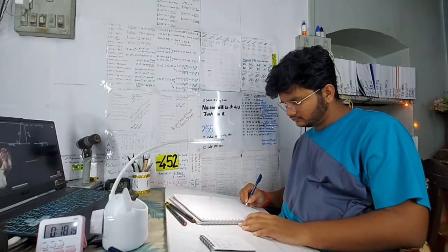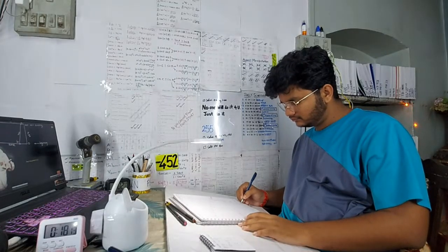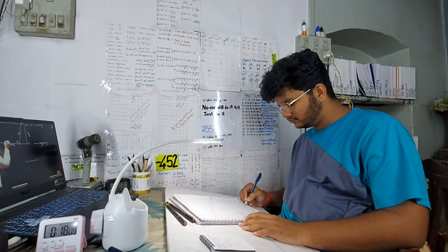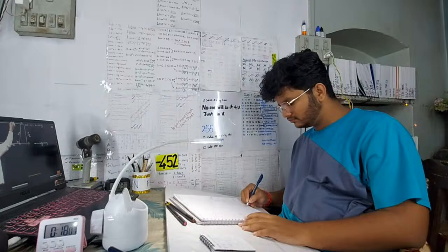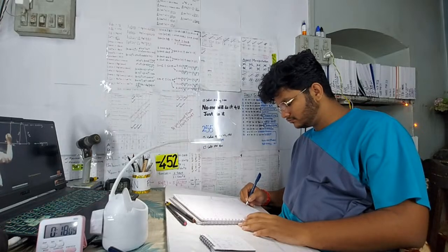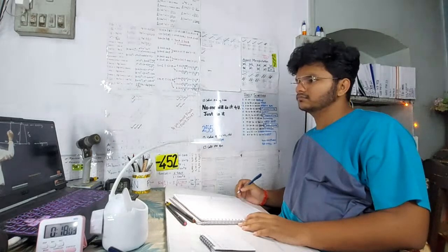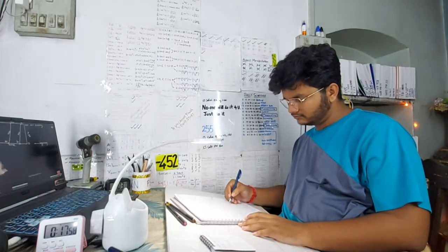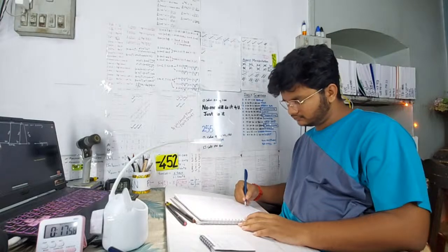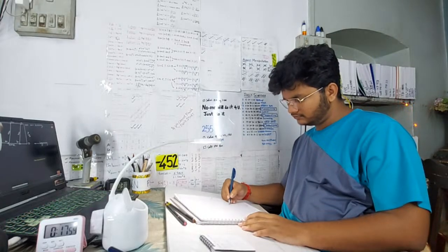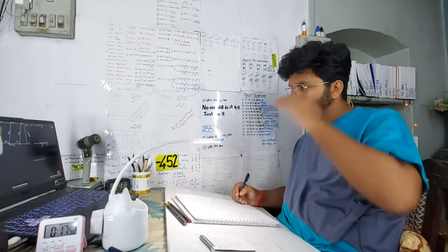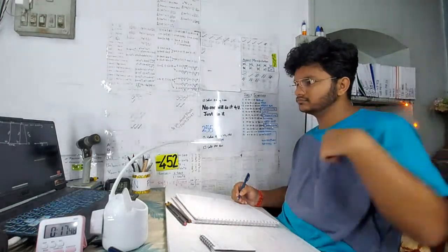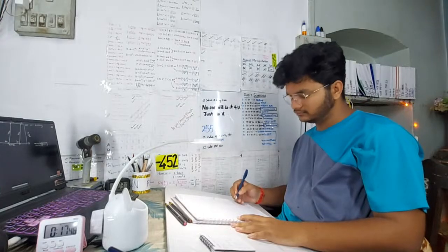Moving ahead. When you identify the second readings, B2 and E2 at 600 degrees centigrade, B2 will come here and E2 will come here. When you join this B2 E2, this is the transformation curve at 600 degrees centigrade. 0 to B2 is the incubation time at 600 degrees centigrade. Similarly, when you plot the third readings B3 and E3, the line joining B3 E3 is the transformation curve at 550 degrees centigrade.